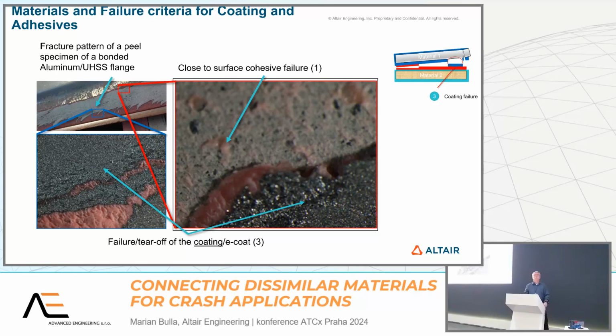And what we see here are pictures from reality, where you see failure of the coating in this area, where it is torn apart from the metal below. So once we have loaded it very highly. And this pink stuff here, this is the adhesive. And here we have the paint, the coating. And here you have the naked material, metal. So we see coating failure in reality, in real tests.